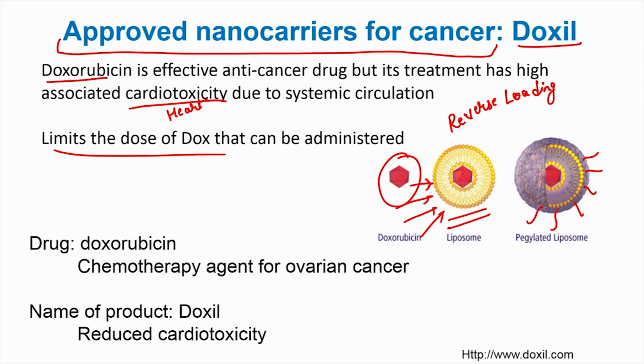So again, I hope you remember PEGylation. PEGylation prevents the interaction of various cells and proteins with your biomaterial surface, and because of that it will not let this particular liposome get absorbed with several proteins or get cleared away by the immune system. So, it increases the residence time, and this resulted in quite a bit of effectiveness.